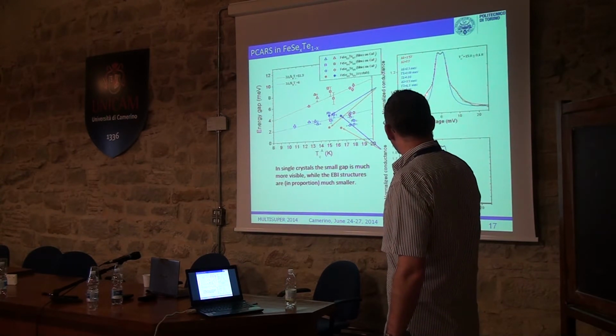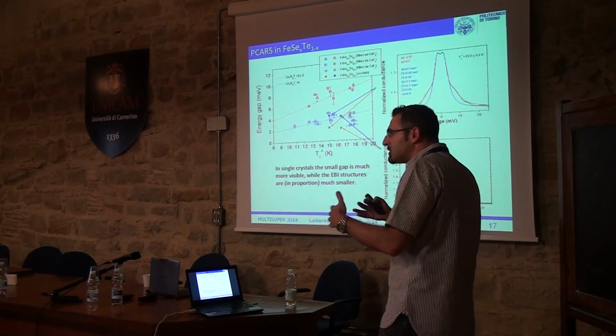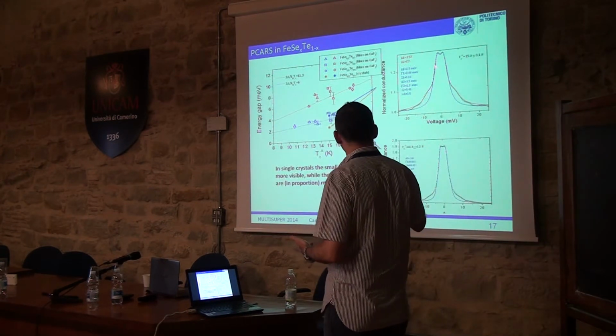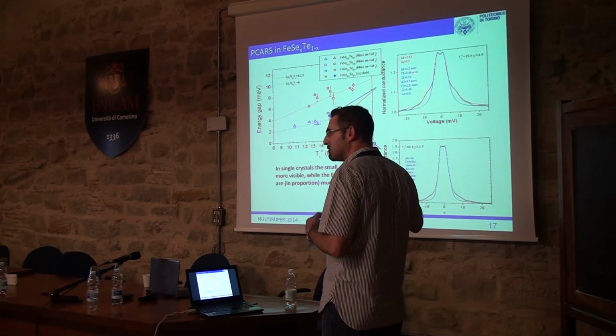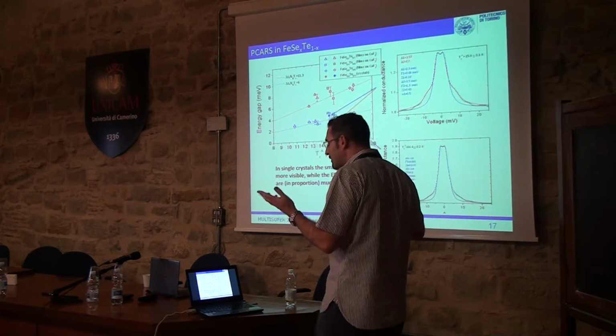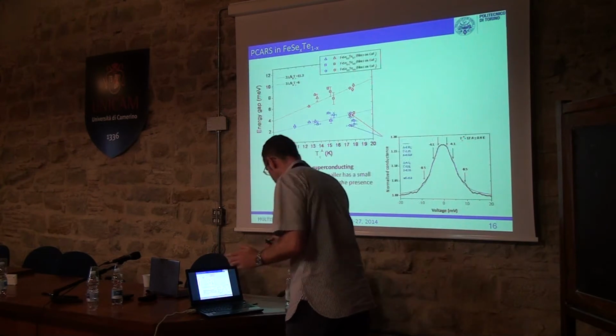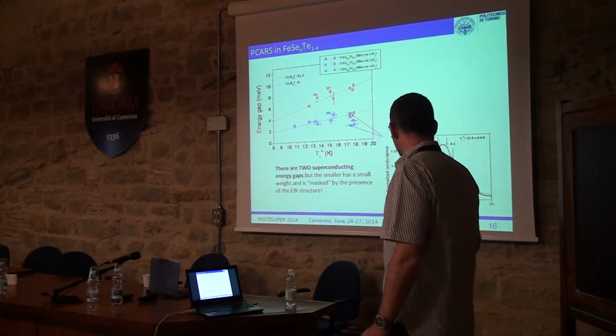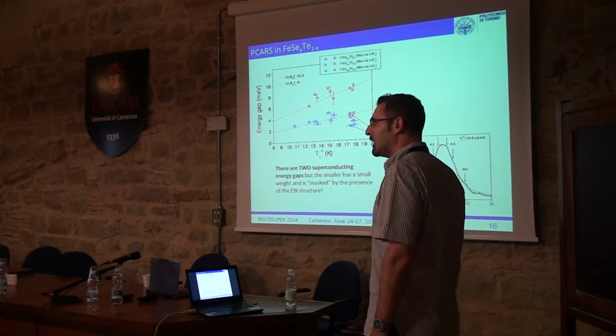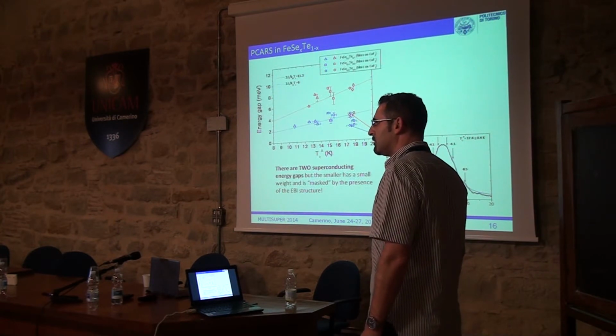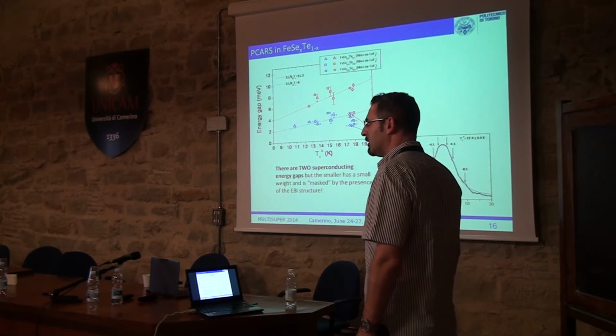So I don't know the reason why this should have almost always the same weight, but it's the fact that the superconductivity signal in crystals is much higher. This curve is an exception. This one, I have no explanation why. You don't see very clearly this picture. I don't know. But in the theory, what do you do to see or not the boson? So you don't have a specific parameter.